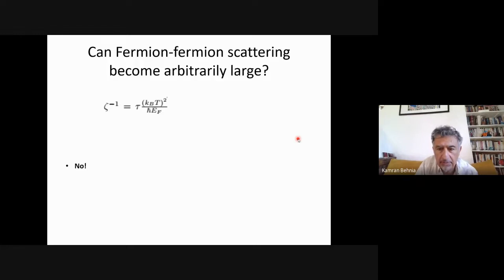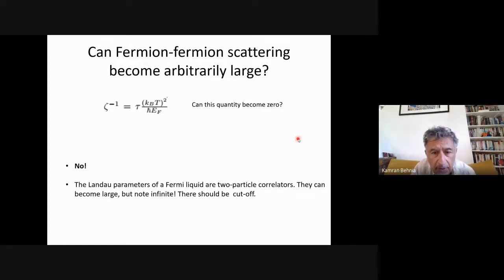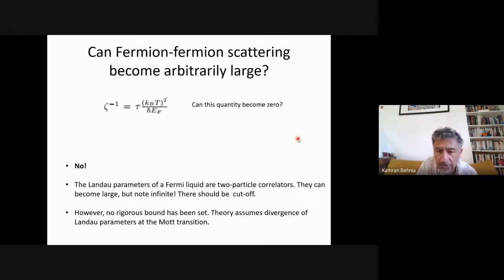Why does the Fermi liquid disappear at a given pressure in helium-3? I speculate that this is because this quantity cannot become arbitrarily large. Zeta cannot become arbitrarily large. The Landau parameters are two-particle correlators. They can become large, but they cannot become infinite. There should be some cutoff. Of course, there is no rigorous theory putting this bound. All theoretical treatments I am aware of assume that the Landau parameters diverge at the Mott transition, but experimentally this is not the case. Helium-3 is a Fermi liquid, it remains a Fermi liquid, and suddenly at some particular pressure, when these Landau parameters are huge but not infinite, the system ceases to be a Fermi liquid.